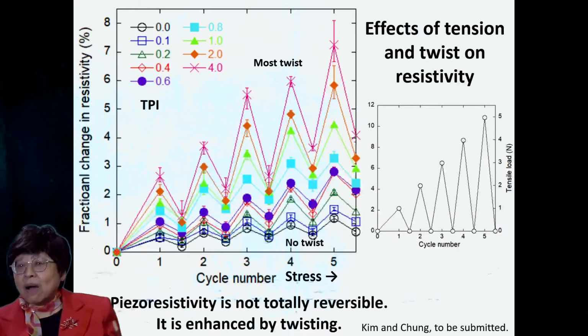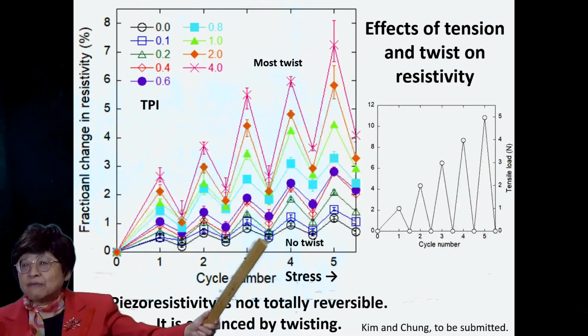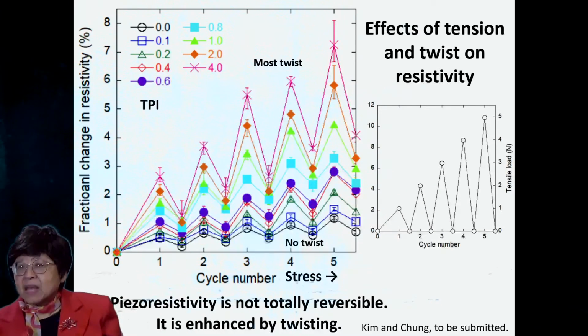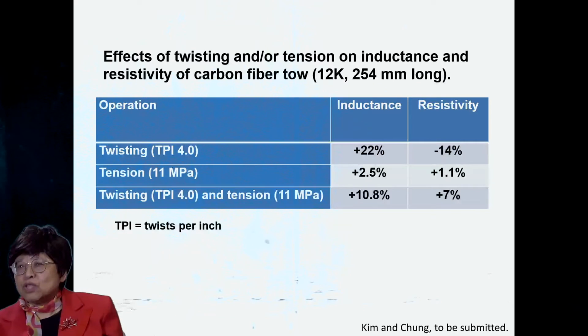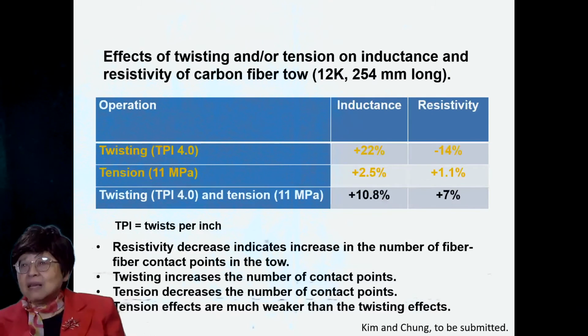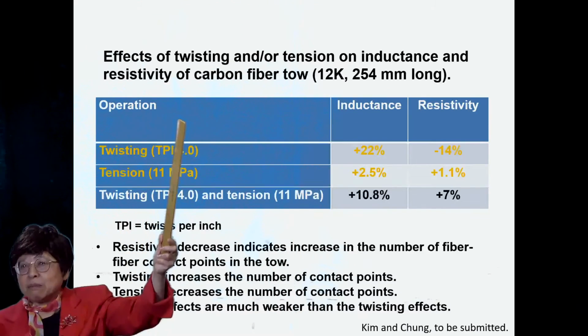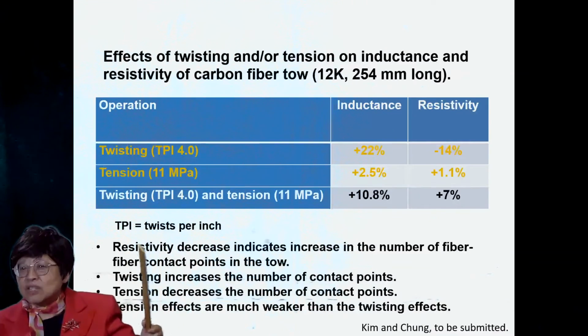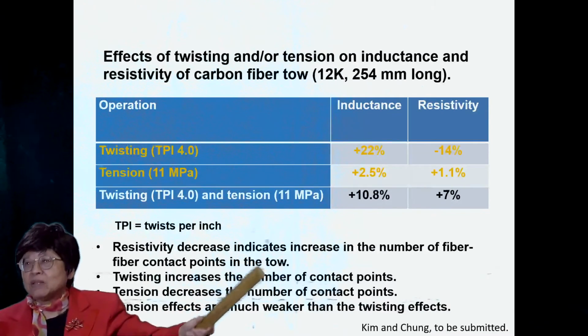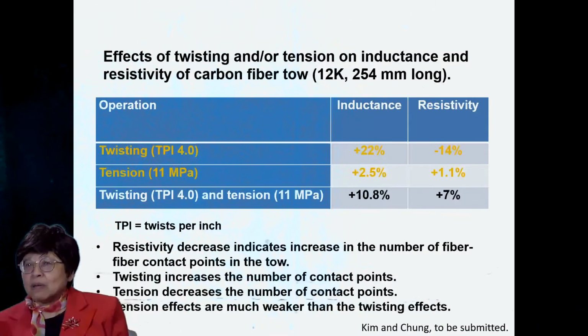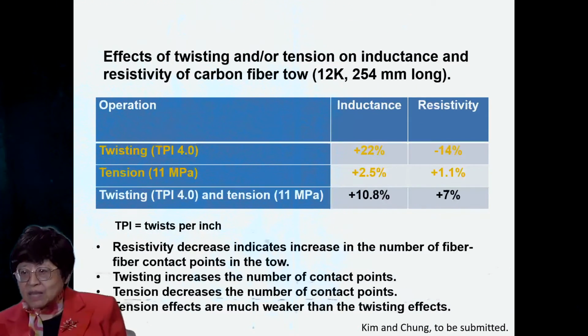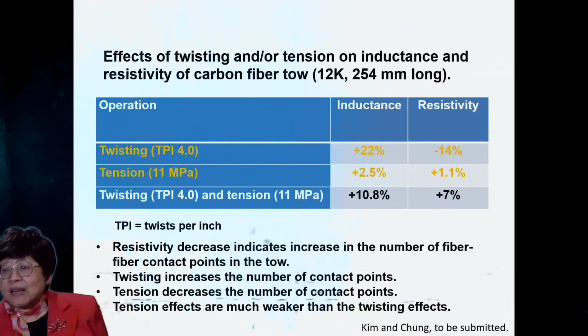Now the resistivity likewise increases upon tension, and the effect is more if one has more twisting. Let's compare these fractional changes in the inductance and resistivity. The twisting here, or the resistivity decrease, indicates increase in the number of fiber-fiber contact points in the tow, and twisting increases the number of contact points. However, tension decreases the number of contact points, so the resistivity increases for the tension but decreases for the twisting. Note that the tension effects are much weaker than the twisting effects.